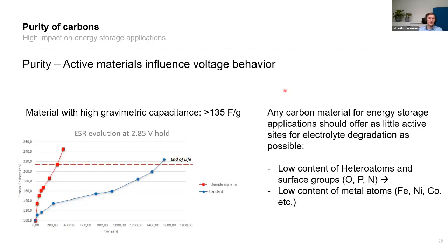Another thing is purity. One thing that we do in supercapacitors, of course, is lifetime testing. We had this one material by an industrial carbon manufacturer that they sent to us, and it had very high gravimetric capacitance, 135 Farads per gram, or 35% higher than what you get with normal activated carbon. This was also carried over into volumetric capacitance, so very nice volumetric capacitance. But as soon as you did the lifetime test, you could see that this carbon, instead of surviving 1,500 hours at 65 degrees C and 2.85 volt, only survived around 200 hours.